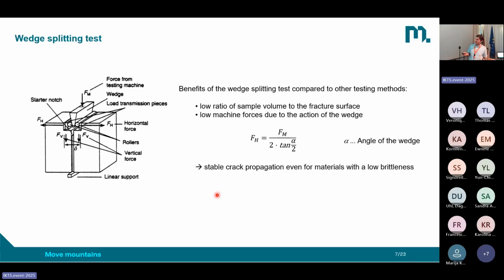And the other very beneficial fact is the relation between the forces, because here you see how we can calculate the horizontal force from the machine force, and for an angle of roughly 10 degrees, we have a factor of 5. This means the horizontal force here is 5 times higher than the vertical force in the machine. And this for sure decreases the elastic energy in the machine, again making fracture more stable.